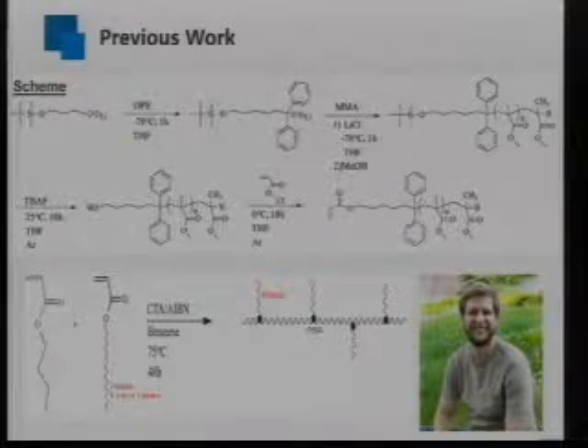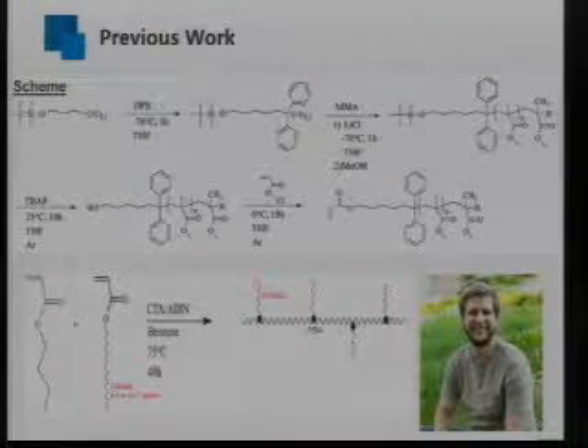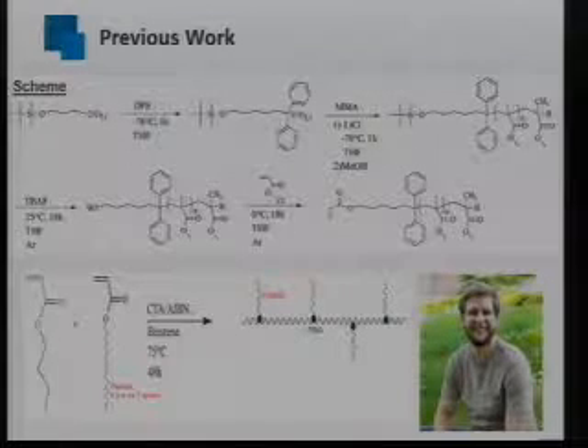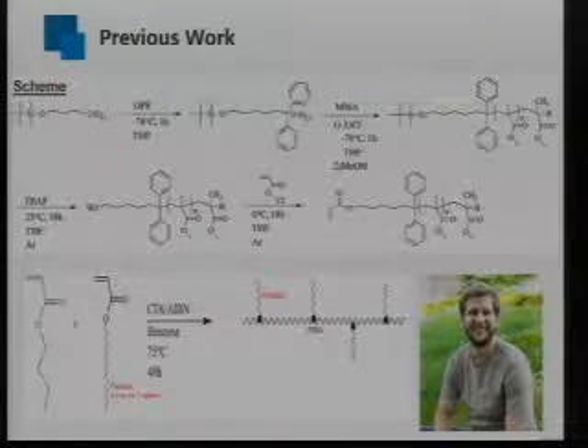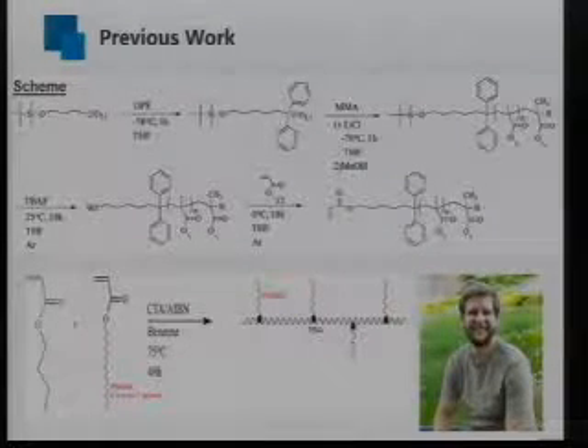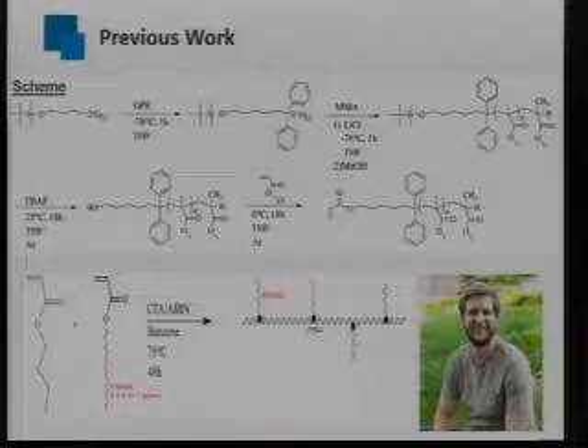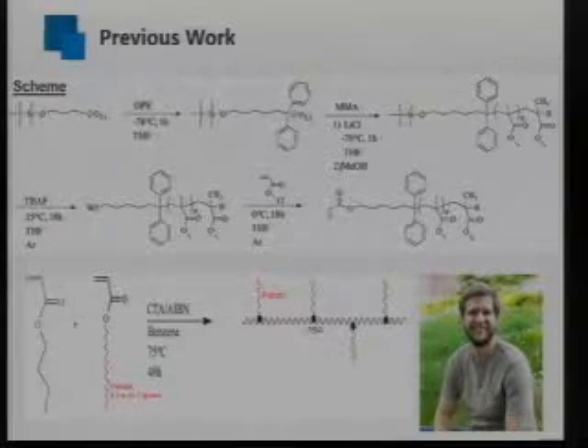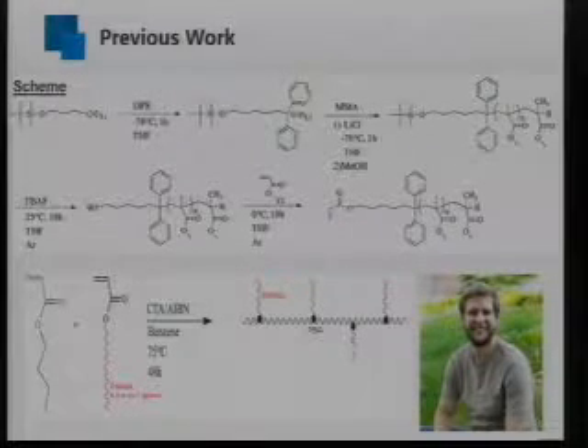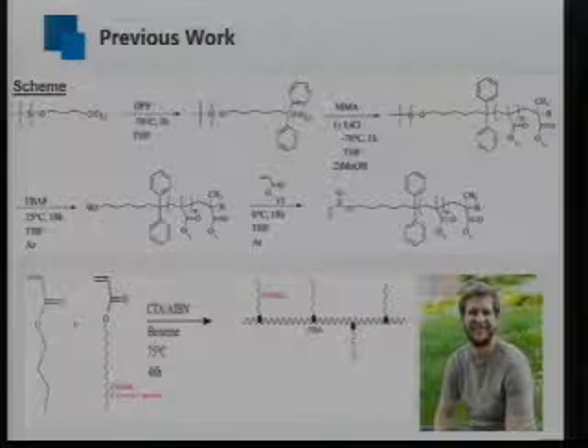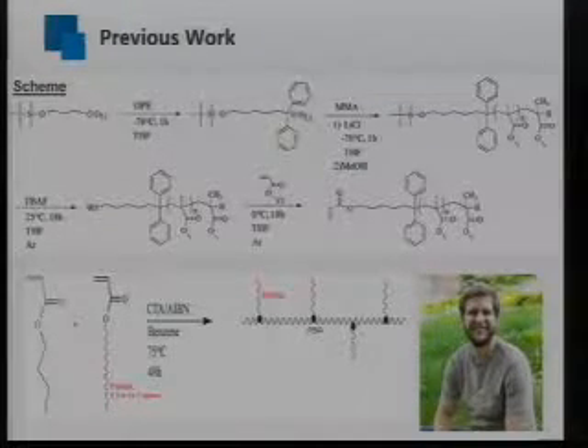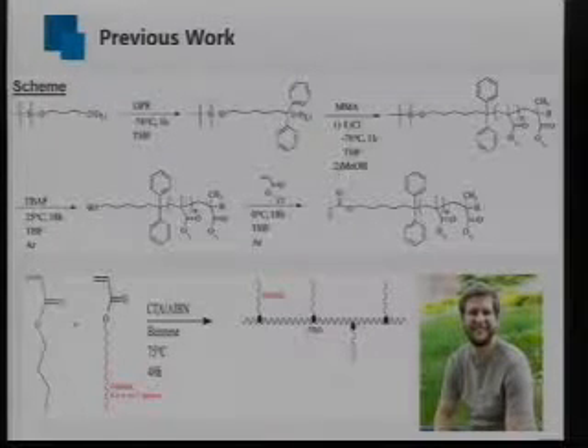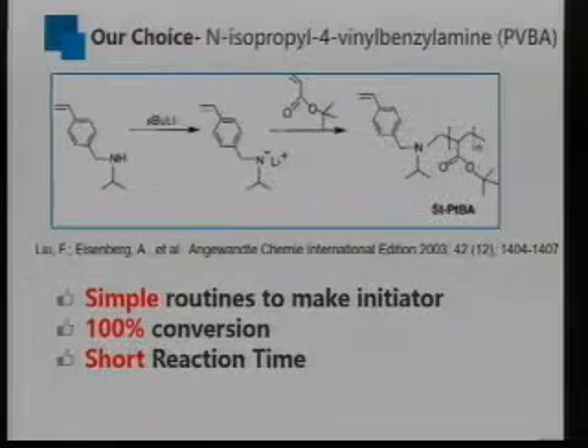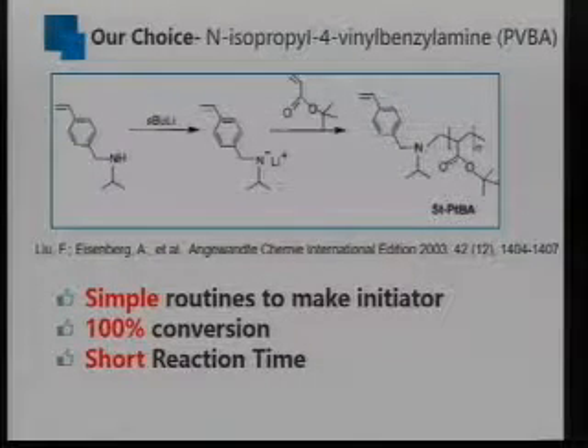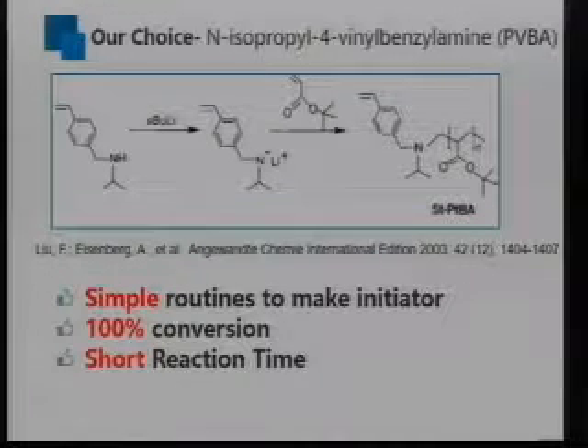This PMMA macromonomer was synthesized by anionic polymerization using hydroxyl-protected sec-butyl lithium as the initiator. After the deprotection of this hydroxyl group, it can be linked with acryloyl chloride to make the final macromonomer. However, this approach requires very complex operations. The linking reaction itself needs a very long reaction time and has very limited conversion. In this way, it's very hard to make large amounts of the polymer samples to meet the requirement for tensile study. As a modification, we found this new initiator called N-isopropyl 4-vinylbenzylamine, in short PVBA.